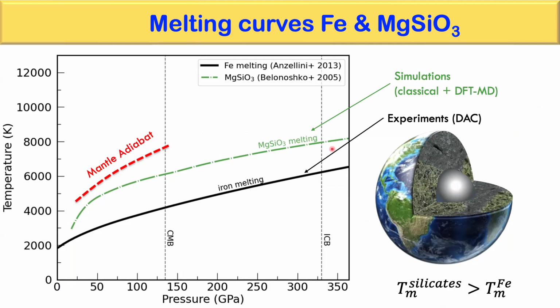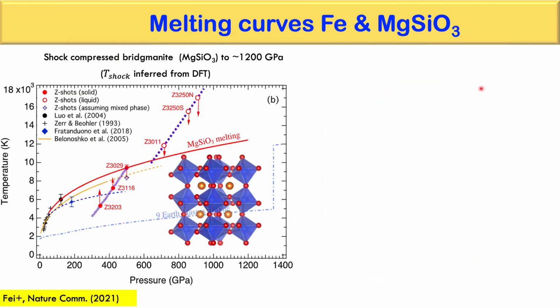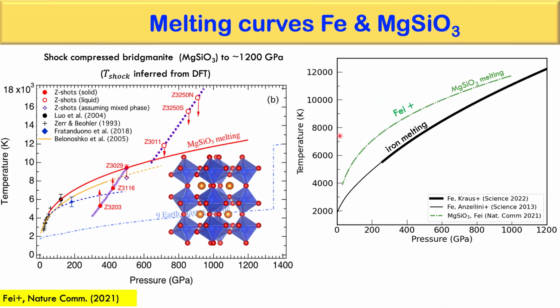But for materials in the mantle, for the very, very high pressure regime, there are actually not many experiments available. And most of the estimates come from simulations. So one of the few experiments that has been done at the really extreme hundreds of gigapascal regime, the megabar regime, is this one by Yingwei Fei, where they shock compressed enstatite, which is a bridgemanite in this case, a high pressure polymorph representative of the mantle, and they constrained just one point here when it intersected the melting line. And they drew a melting line that looks like this. Again, higher than the melting line of iron, no surprise, but we have a constraint at higher pressure. It's not just an extrapolation.